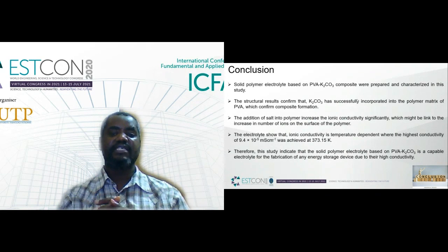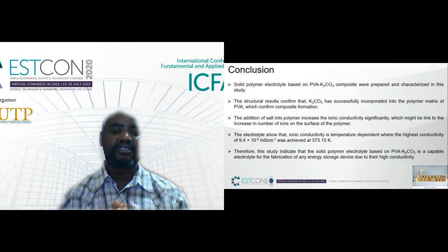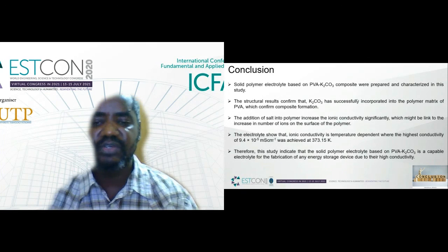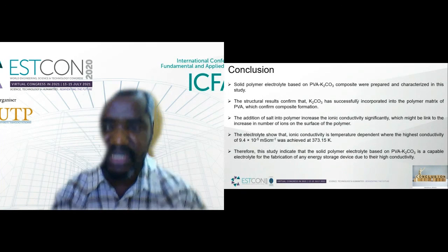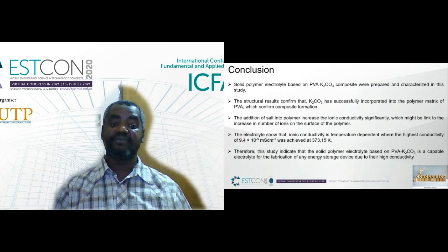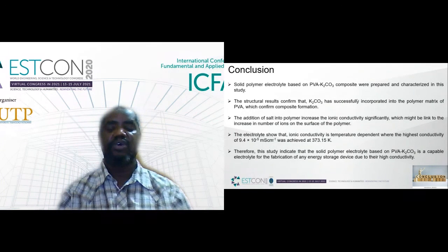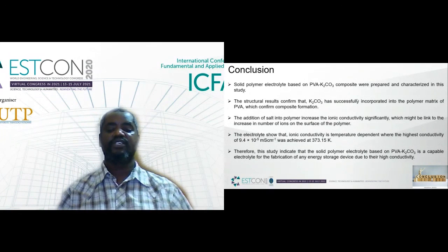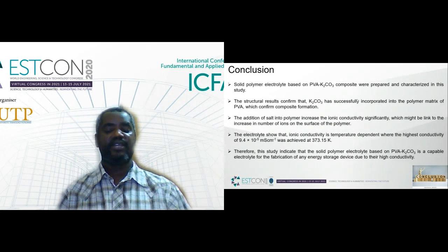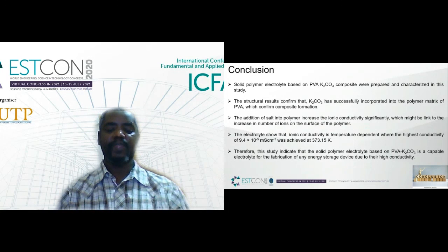The electrolytes showed that ionic conductivity is temperature dependent, where the highest conductivity of 9.4 times 10 to the minus 5 millisiemens per centimeter was achieved at 373.15 Kelvin or 100 degrees C. Therefore, we can say this study indicates that the solid polymer electrolyte based on PVA and potassium carbonate can be used as a capable electrolyte for the fabrication of any energy storage device due to its higher ionic conductivity.